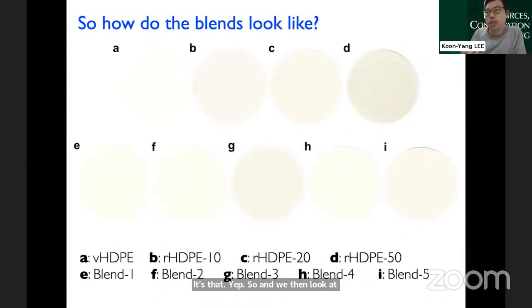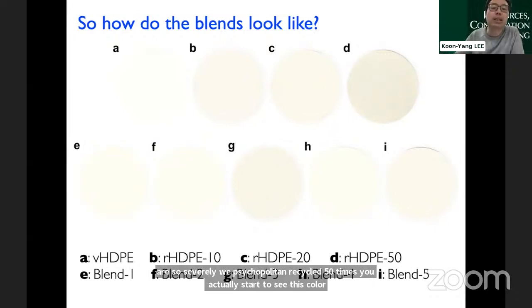So to the milk bottle industry, color is a very important indicator, because as a consumer, when you look at a bottle, you may choose not to buy that particular brand just because it looks a little bit off-white. So here from image A to I, there are the different types of the polymers, the different types of blends. So A from virgin polyethylene, so top row A, B, C, D, virgin polyethylene, recycled 10 times, 20 times, 50 times. E, F, G, H, I are the different blends from blend 1 all the way to blend 5. Right. So obviously looking at image D there, severely recycled polyethylene, these are polyethylene recycled 50 times, you actually start to see discoloration itself. Again, this is just because your degradation byproduct stays within the material, and that is actually causing that discoloration.